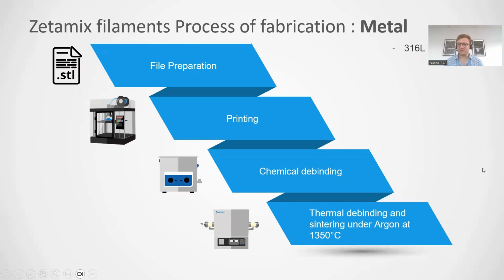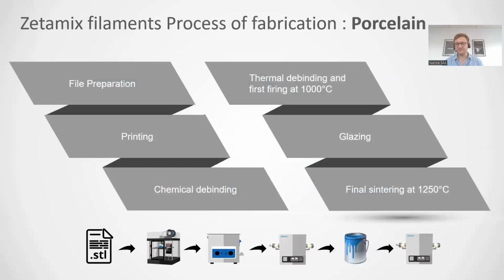So now, if we talk about porcelain, you'll see that the process is slightly different, because most porcelains are going to be glazed, and I'll go back to what glazing is later on, so that adds some steps in the process. It starts in the same way. We print the filament using any FDM printer. Then we dip the part in acetone to remove some of the binder. We do the chemical debinding, and then we fire the part. We go in a furnace, and in that furnace we will first fire the part at 1000 degrees Celsius.